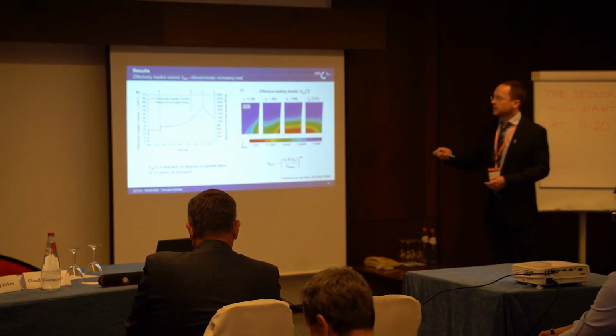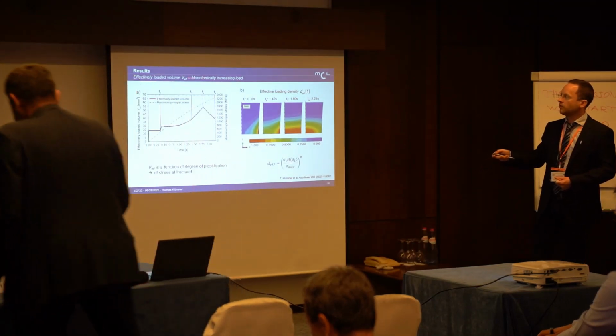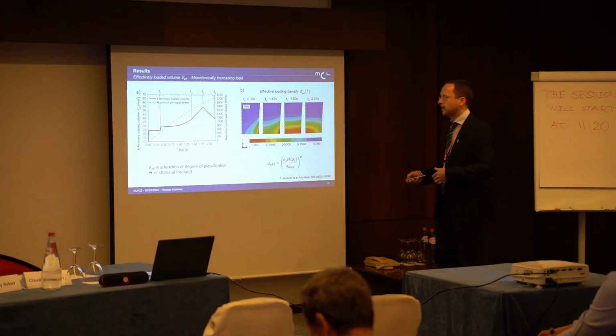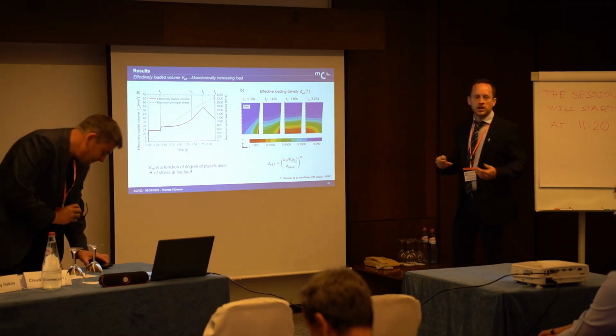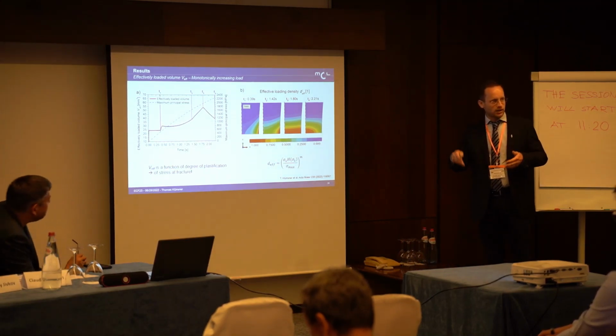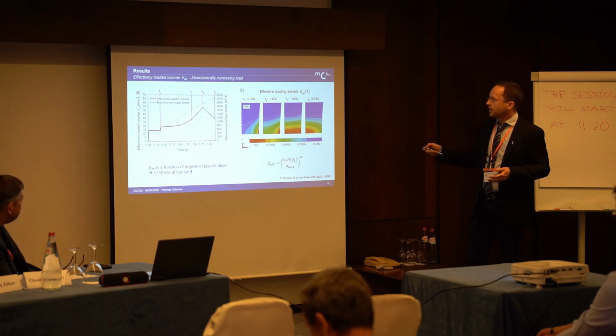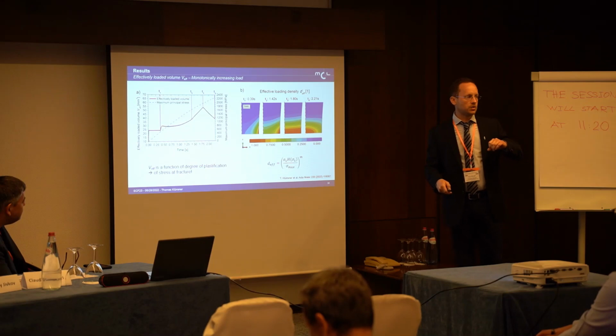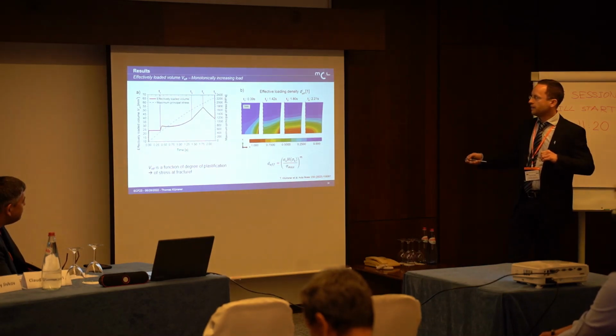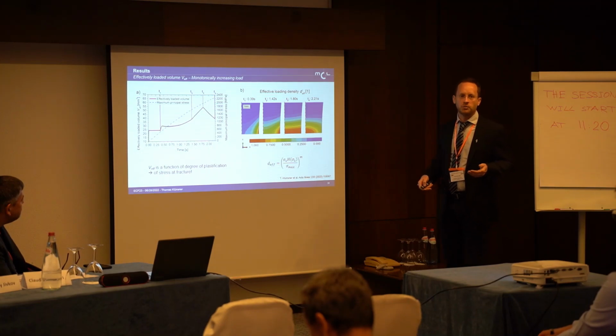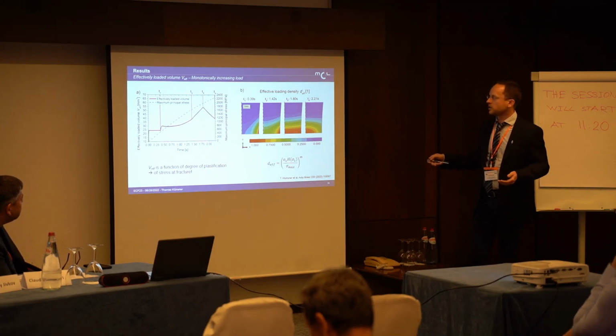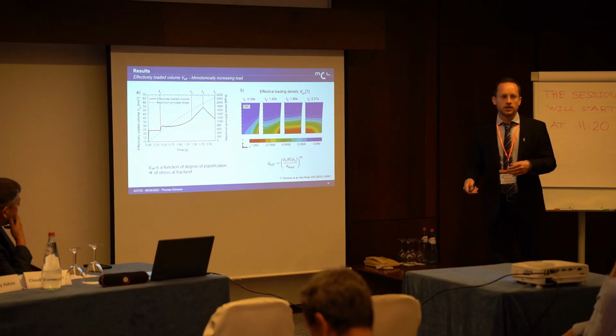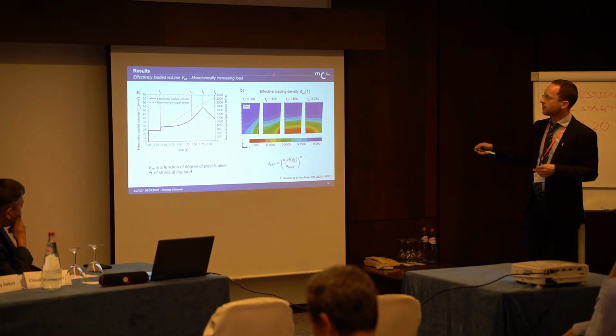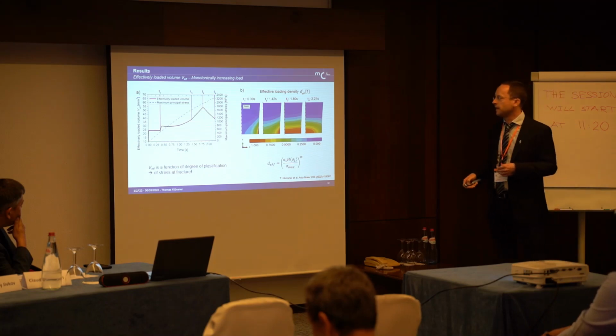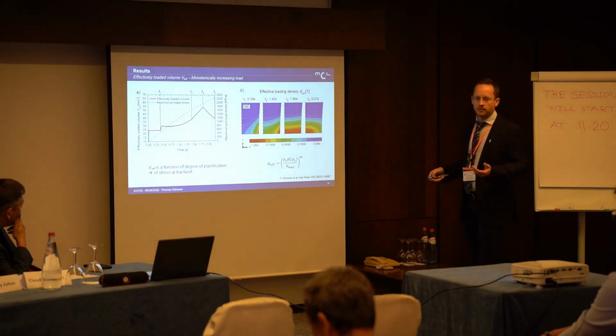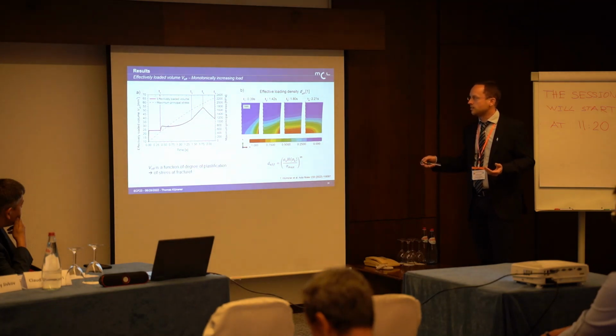And also very interesting, and this supports the idea, is that the effectively loaded volume, as I mentioned before, if we evaluate it numerically for the specimen, does change during loading for monotonically increasing situations. And if we consider that the stress distribution changes during loading due to plastification, you see here a mesh size independent representation of the contributions to BF. I think you can imagine here in the beginning, your stress concentration on the notch root, so to say. This here is on the notch of a radius of 50 millimeters in our specimen. And due to plastification and residual stress buildup, you have an increase in this BF.